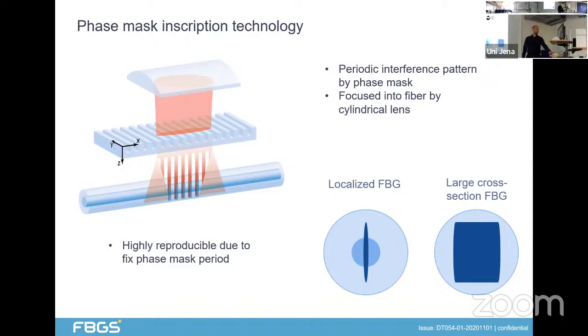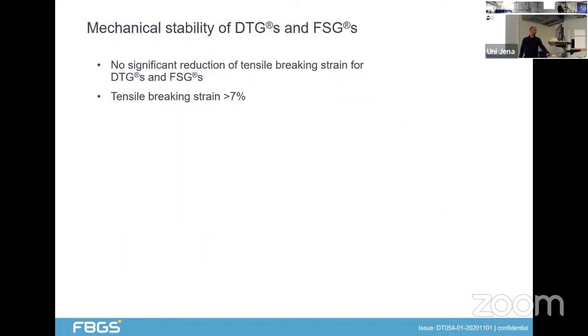So these two techniques, as I said, on one hand the draw tower technique, and on the other side the femtosecond technology, are capable of writing gratings, one before the coating is applied and the second one through the coating. And that means by using these, we get gratings with quite high mechanical stability.